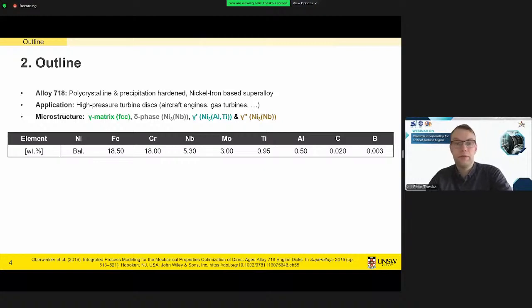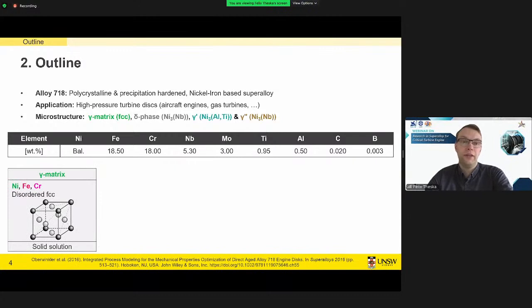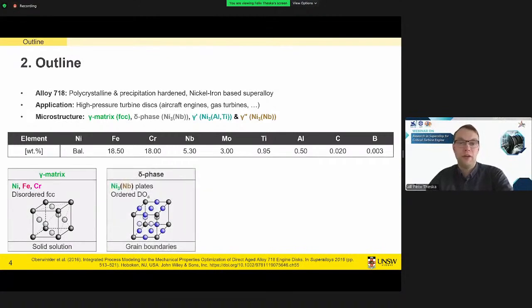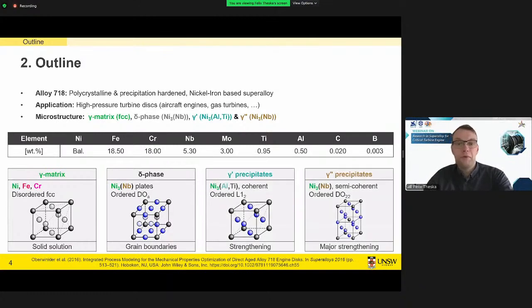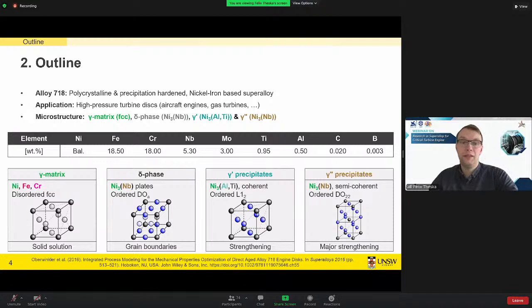As we look into the microstructure of this alloy, we find a face-centered cubic gamma matrix. We find delta phase platelets that are rich in niobium. They are usually in the size of a couple of micrometers, so they're fairly large and decorate the grain boundaries. And then most importantly, we find 2 types of nanometer size precipitates: gamma prime, which is rich in aluminium as well as titanium, and gamma double prime, which is rich in niobium. And these gamma double prime precipitates contribute a major part of the strength of this alloy.